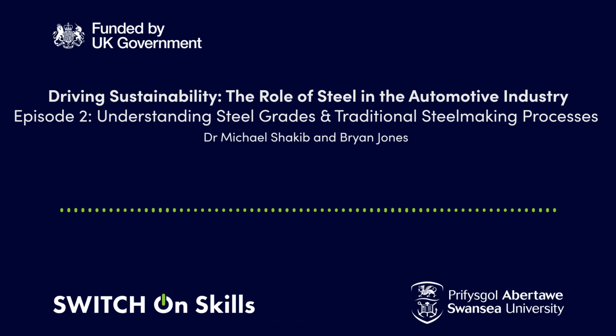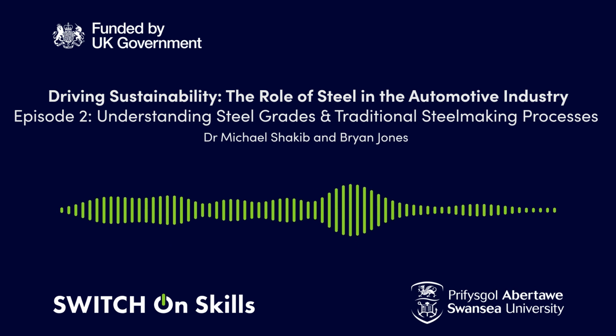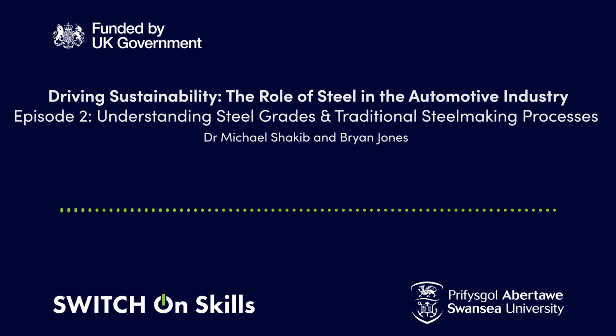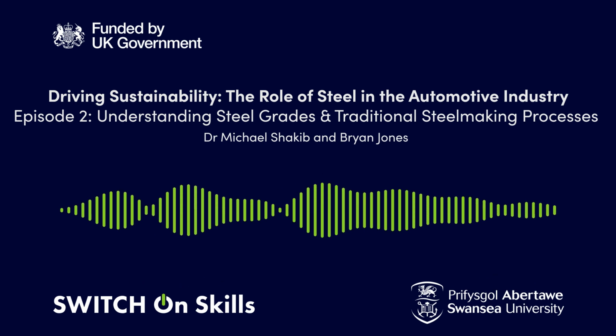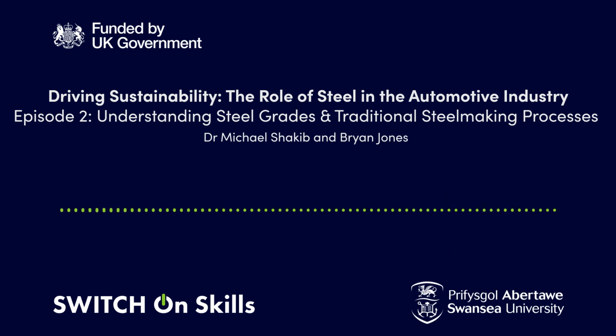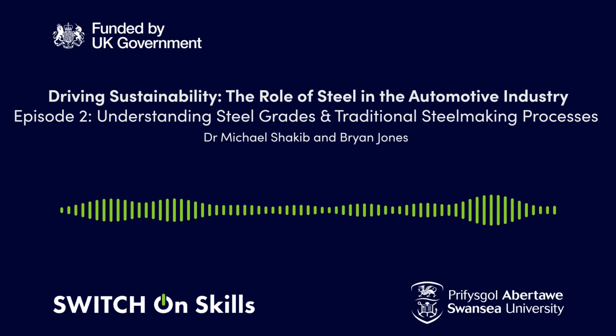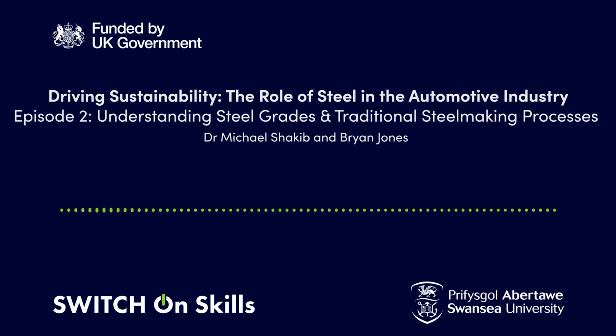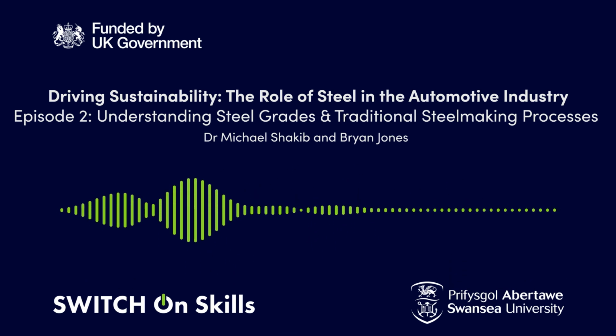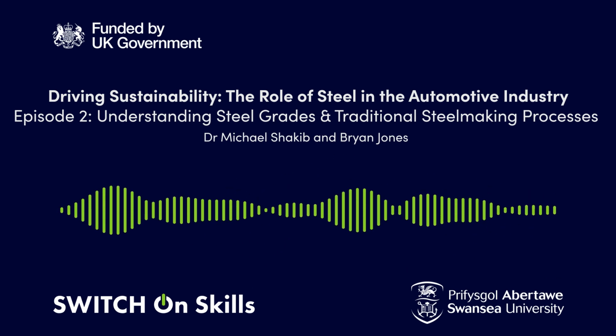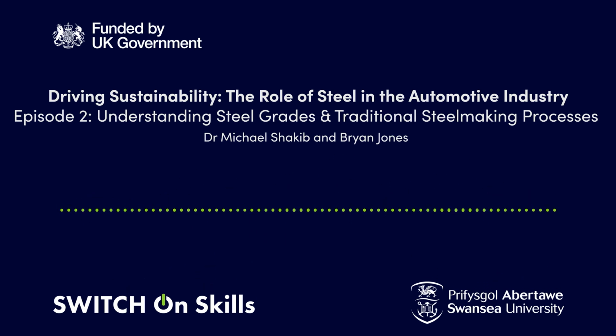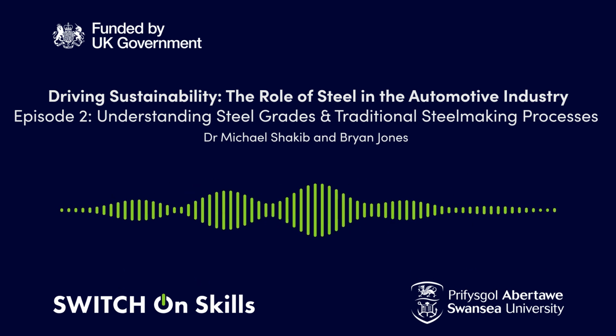From the blast furnace, you've got one product with, as I said, typically 3 or 4% carbon in it. And from the BOS steelmaking process, again, you've got one product, which has a much lower level of carbon and much lower level of other impurities such as silicon and phosphorus. And then you go to the secondary steelmaking, and this is now where you generate a much larger variety of products. So you change the chemistry in the secondary steelmaking process.